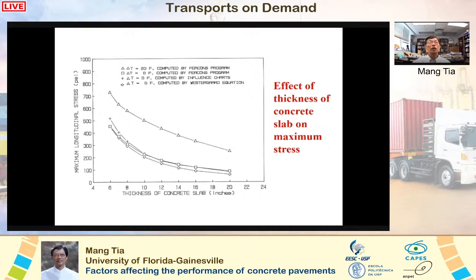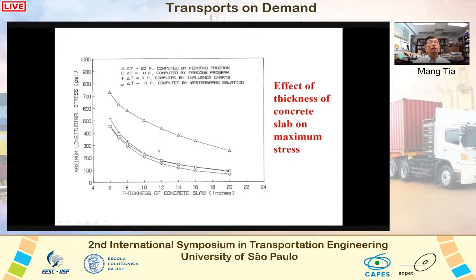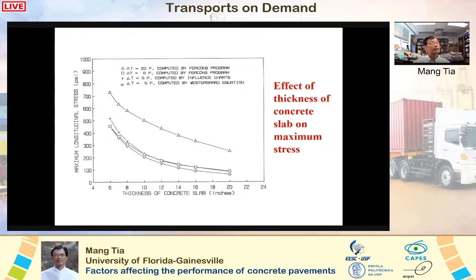These plots show the maximum stresses as a function of slab thickness. The plots on the lower part of the figure are for the condition of no temperature differential in the concrete slab. The plot on the upper part of the figure is for the condition of a temperature differential of plus 20 degrees Fahrenheit. In both cases, the maximum stresses decrease significantly as the slab thickness increases.